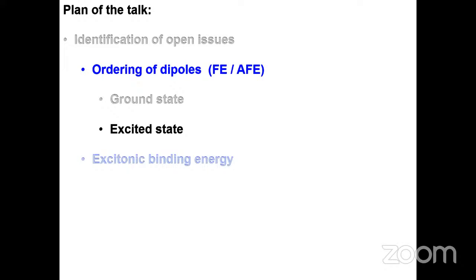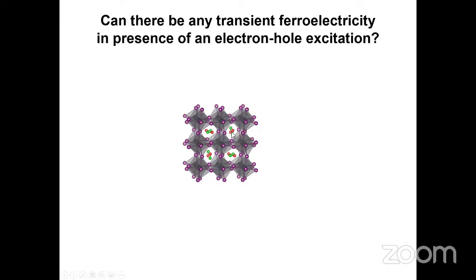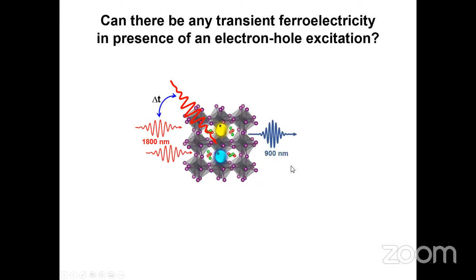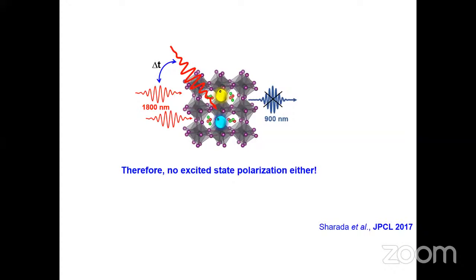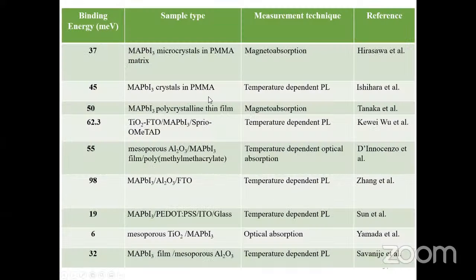And we also addressed this fine question of what happens after the photoexcitation. These are the dipoles that are supposed to be rotating. I come in with a photon, which is high energy, which creates an electron and hole. Then I give it a slight time delay, and at the end of that delay, I measure the second harmonic generation and see if the rotation has stopped and I get a polar signal. I'll just tell you the end result: we did this delay experiment and found that there was no second harmonic generated. So even in the excited state, there is no polarization that develops. So that was settled. I'll just quickly tell you about the exciton binding energy.